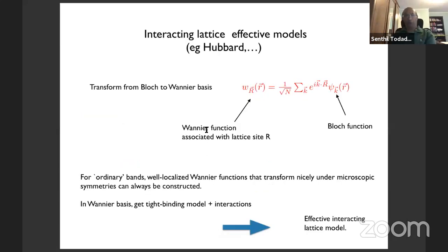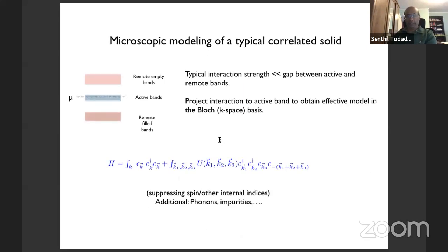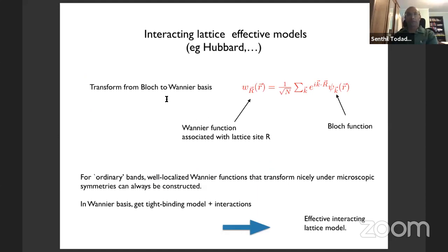Now, we often model correlated electron systems through a lattice effective model, for instance, a Hubbard model. So the way to go from this Bloch basis Hamiltonian to something like a Hubbard model is to transform from the momentum basis to the Wannier basis. So associated with Bloch functions, psi_k(r) in a band, you do this lattice Fourier transform, you get these Wannier functions, which are associated with lattice sites R, and there are some functions of little r, which are centered at some lattice sites capital R. So this is a change of basis.